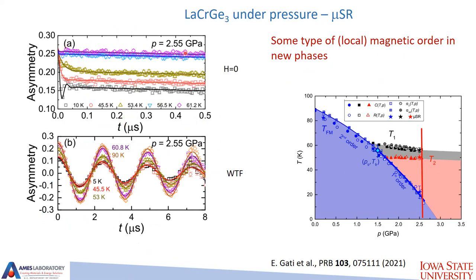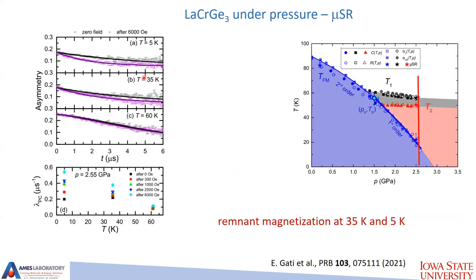You can see a difference in damping between temperatures above the T1 line and temperatures below the T1 line, and the same with the signal from the cell. You can do very specific muon measurements when you look for remnant magnetization. And you can see some remnants, you can see a different damping in zero field and in zero field after 6000 Oe at 5 K and 35 K, so basically here and here, but not at 60, not here.